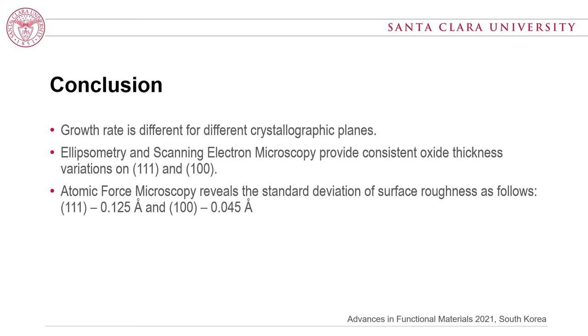In conclusion: growth rate is different for different crystallographic planes. Ellipsometry and SEM provide consistent oxide thickness variations between the 111 plane and 100 plane. AFM reveals that the standard deviation of surface roughness is 0.125 Å for the 111 plane and 0.045 Å for the 100 plane.